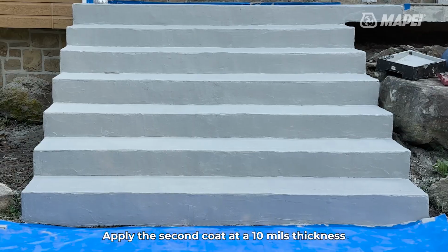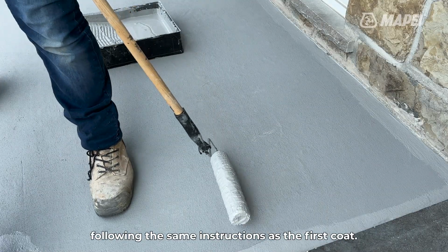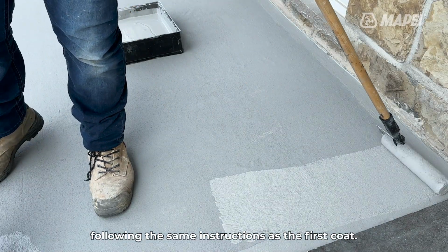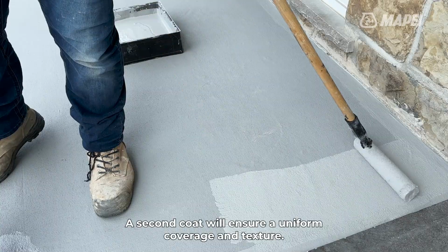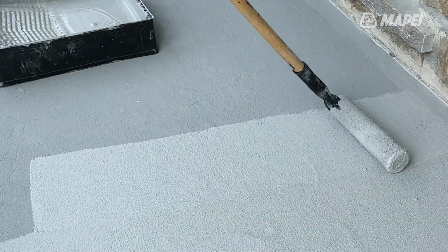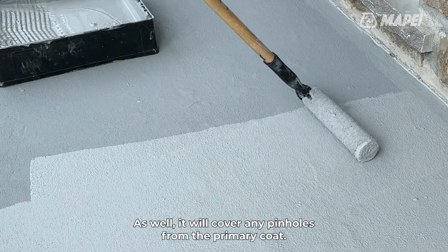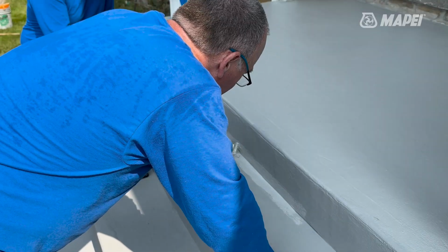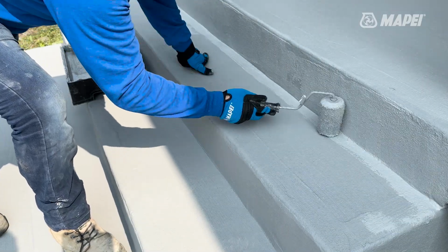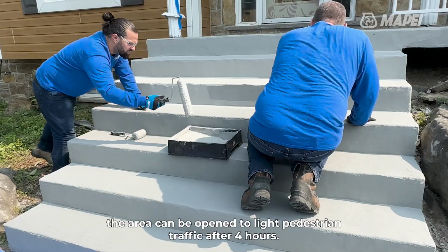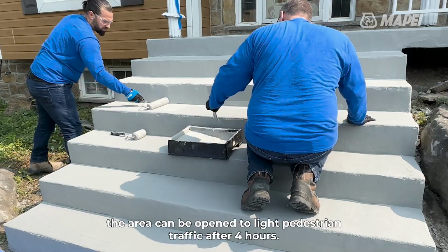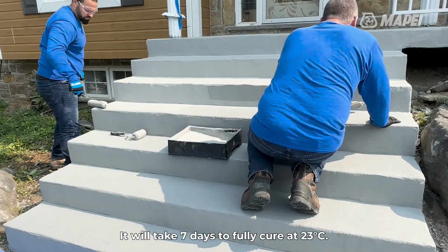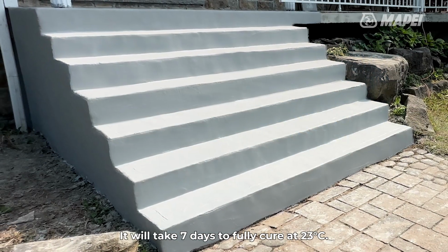Apply the second coat at a 10 mils thickness, following the same instructions as the first coat. A second coat will ensure uniform coverage and texture. As well, it will cover any pinholes from the primary coat. Once the second coat is applied, the area can be open to light pedestrian traffic after 4 hours. It will take 7 days to fully cure at 23 degrees Celsius.